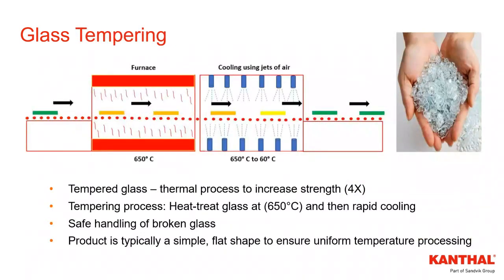And then the last intro slide, just a little bit more detail on glass tempering. Essentially, tempering is a process that increases the strength of the glass by a factor of 4. It's a heat treat process conducted in a higher temperature furnace, about 650 centigrade or 1200 Fahrenheit. It goes through the furnace, and then it undergoes a rapid cooling. That's cooling on both sides of the glass as it passes through an air cooling chamber. And this process locks the outer surface in compression and the core of the glass in tension.